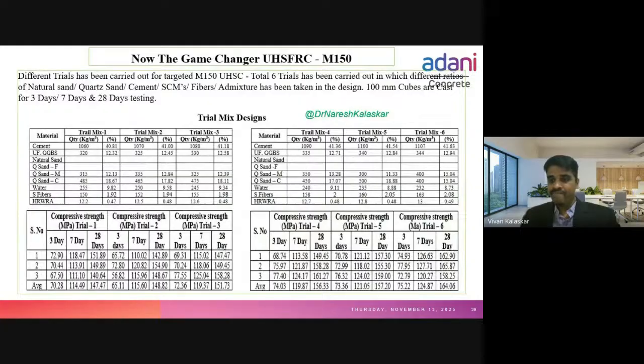This is M150. In M150, we have used medium quartz sand and coarser quartz sand. And in this trial 6, we have used 50-50%. Medium quartz sand 50%, coarser quartz sand 50%. So what is happening? Here, please understand, the coarser quartz sand voids will be filled with medium quartz sand. The medium quartz sand voids will be filled with cement paste, and cement paste voids will be filled with ultrafine GGBS. So when you plan your total density matrix perfectly, then only you can achieve the perfect compressive strength.